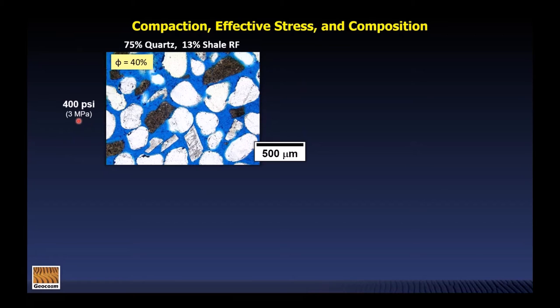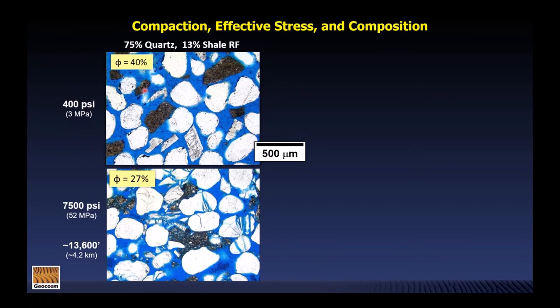Now, we took an equivalent pack to this one, and we put it under much higher effective stress. And as you'd expect, we went from this initial porosity here, you can see the blue-dyed epoxy, of about 40%, down to about 27% when we raised the effective stress to about 52 megapascals. Now, this would be equivalent to a little bit over 4 kilometers of burial under hydrostatic fluid conditions. And I should say that this intergranular porosity here is quite consistent with what we observe in nature for sandstones with this type of composition and texture.